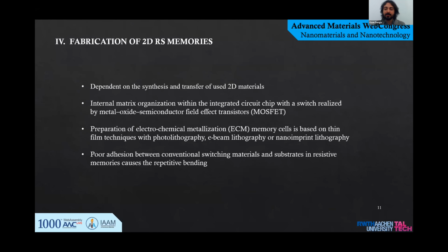The fabrication of 2D RS memories is highly dependent on the synthesis and transfer of the used 2D materials. To give some insight, most solid-state memories in nanoelectronics have an internal matrix organization within the integrated circuit chip, with a switch realized by a MOSFET on each node. Also, preparation of ECM memory cells is based on thin film techniques for nanostructures, and poor adhesion between conventional switching materials and substrates in resistive memories causes the repetitive bending, which results in detachment and cracking.